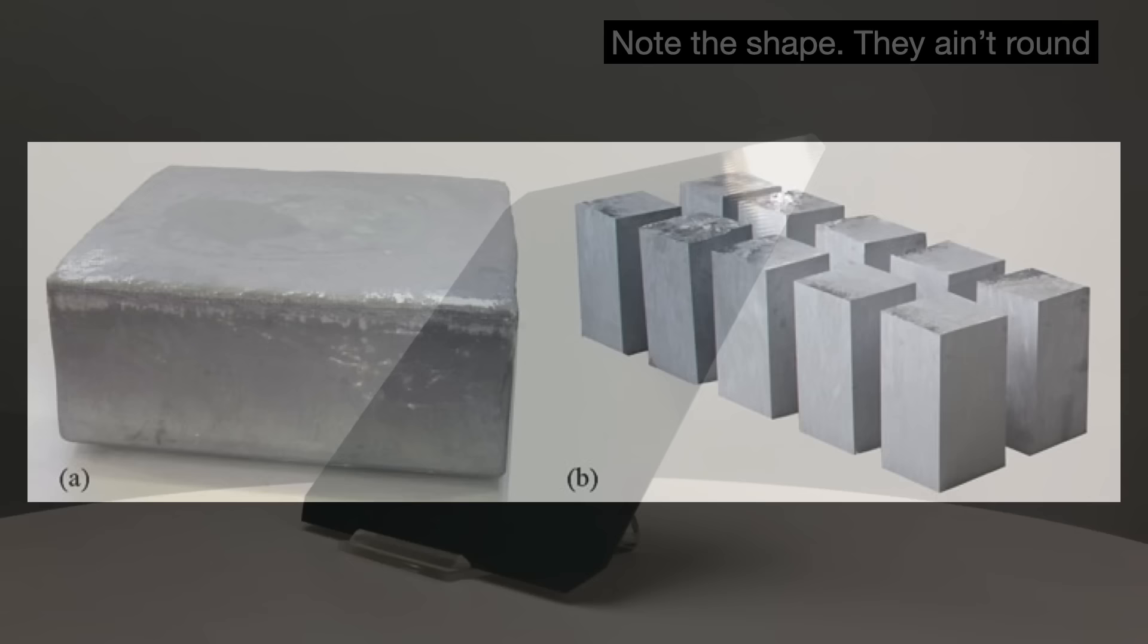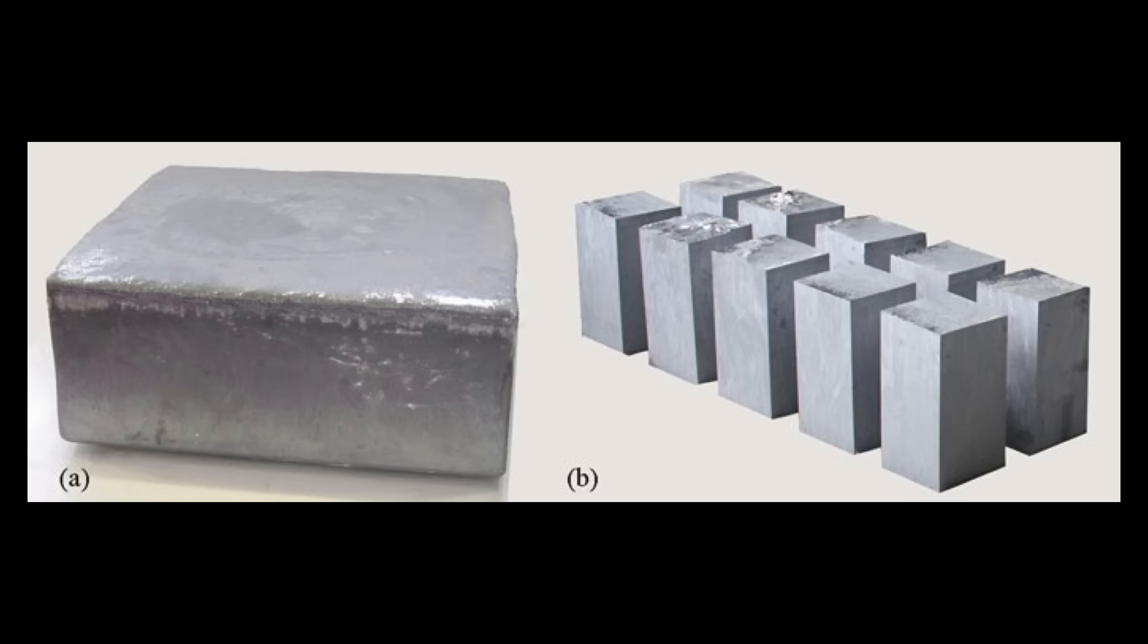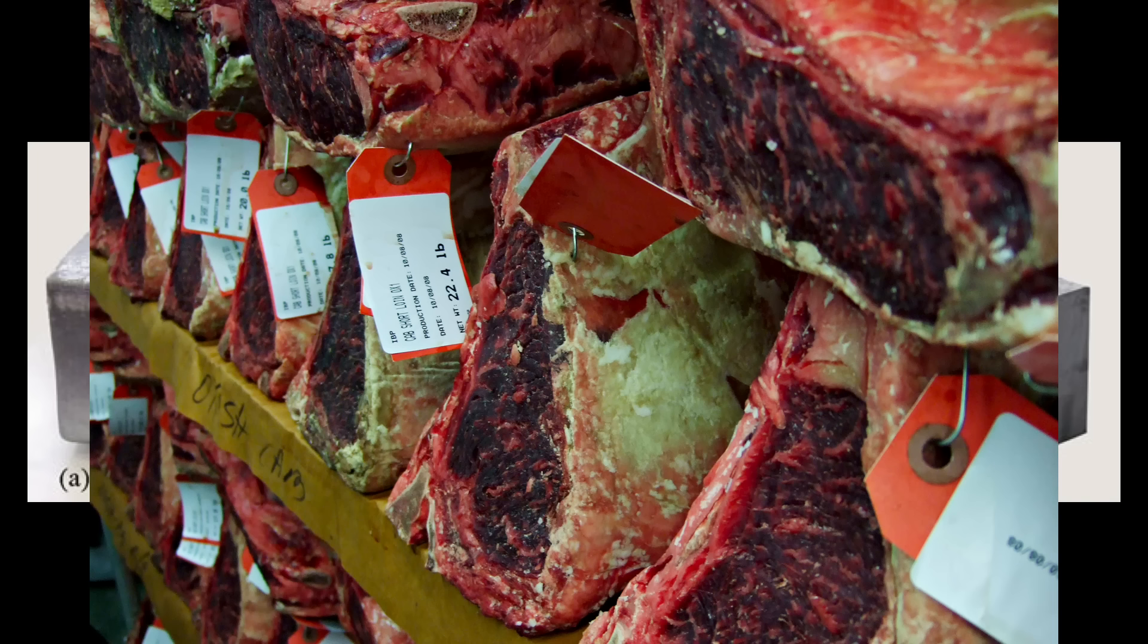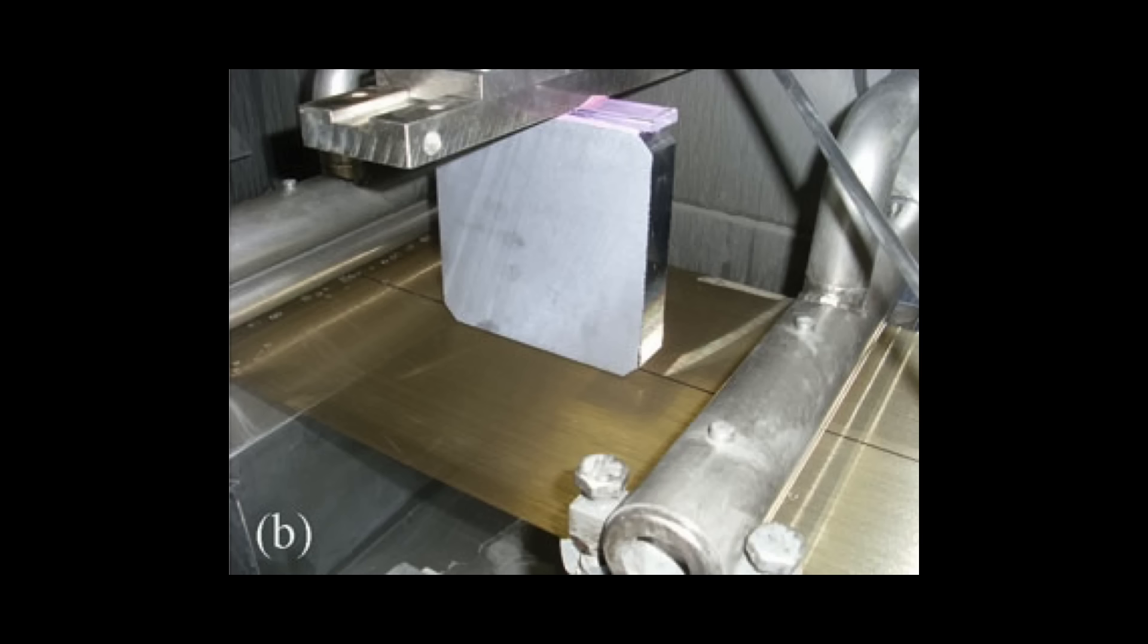The crystals are cut into ingots using diamond-coated saws. For multi-crystal silicon slabs, the outsides are contaminated and have to be chopped off. I am somehow reminded of a dry-aged piece of beef. Then the slicing. We take a steel wire and an abrasive slurry made up of a glycol fluid and a commercially standardized silicon carbide grit powder. You are essentially scratching the powder particles over the crystal using the wire. Modern machines can produce about 2,000 to 4,000 wafers from an ingot in a single run. Each wafer is generally about 200 to 300 microns thick. The goal is to produce as many wafers as possible with a minimum loss of silicon and powder grit. And they take it super seriously. They model everything from wire friction to slurry properties in the computer.